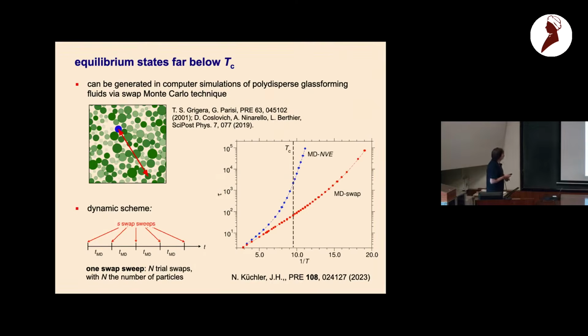To access equilibrium states far below Tc, a nice technique that one can unfortunately only apply to polydispersed systems is the swap Monte Carlo technique. When one has a polydispersed system, one chooses randomly a pair of particles and swaps their diameters. One can introduce a dynamic scheme where one combines the swap Monte Carlo with molecular dynamics. So every so-and-so MD steps, one performs several swap sweeps, and with this one gets a fast method to get to equilibrium states which are far below Tc and close to the experimental glass transition temperature.